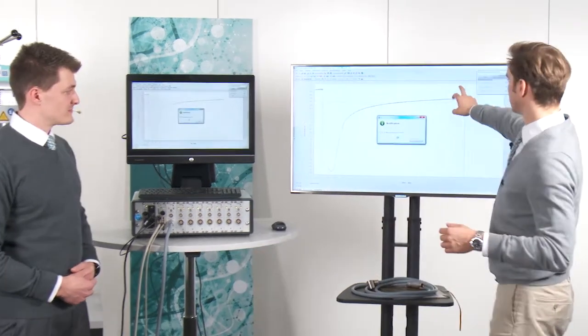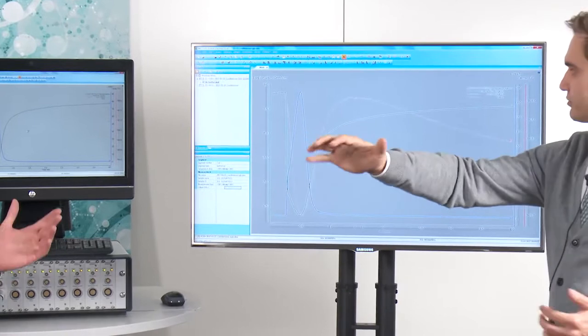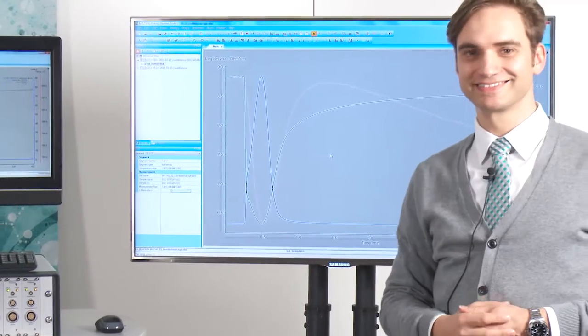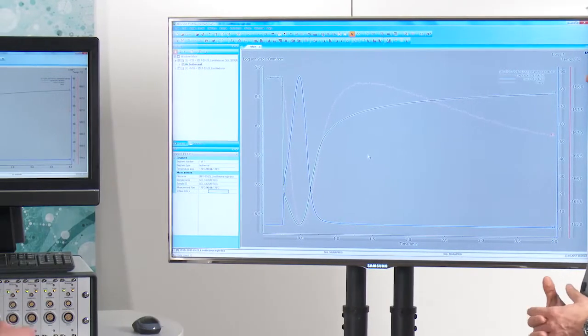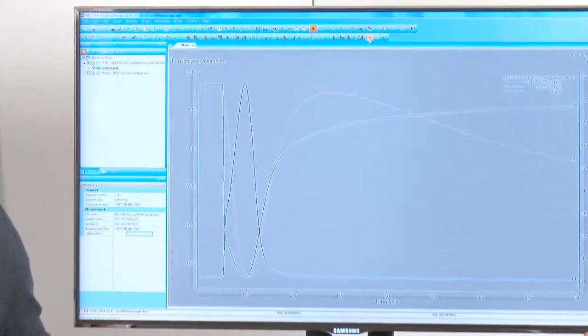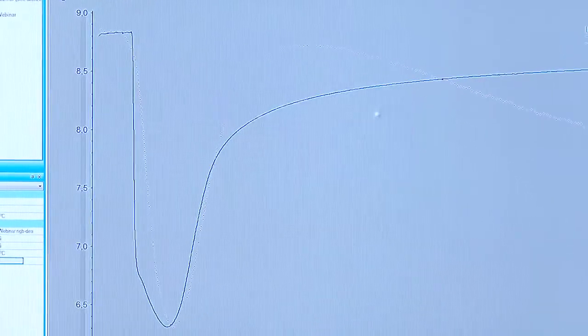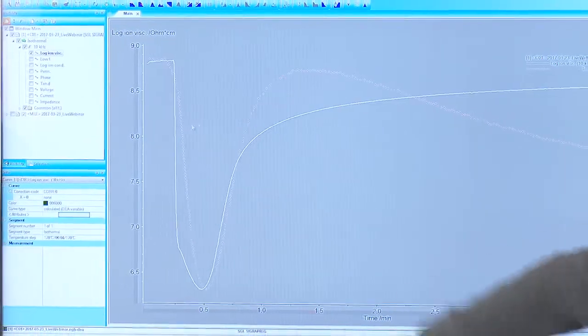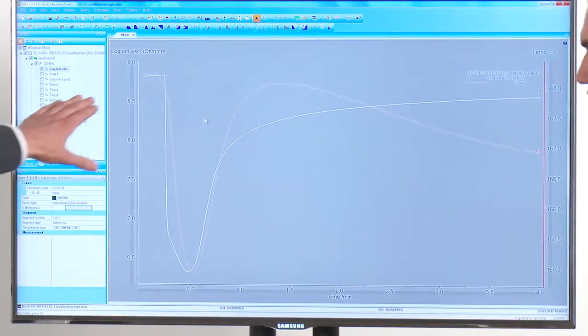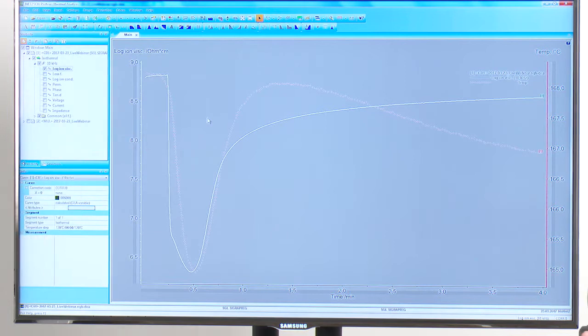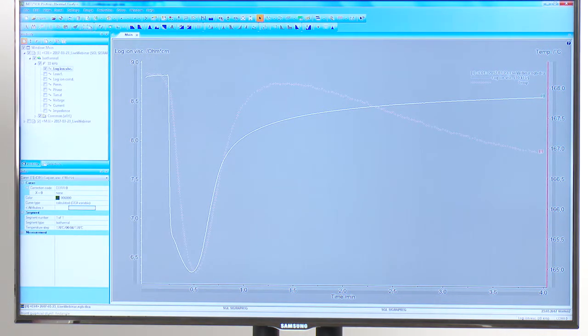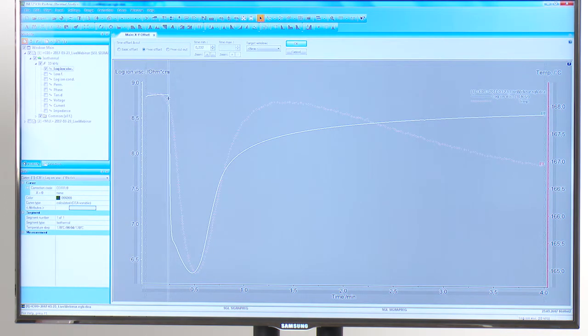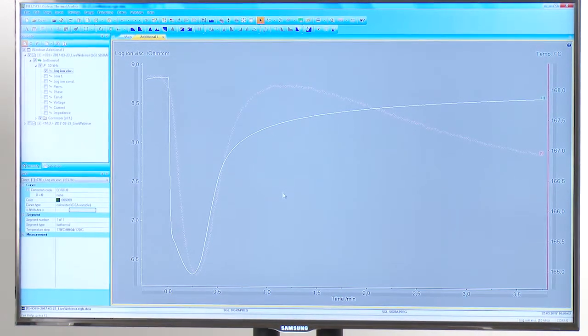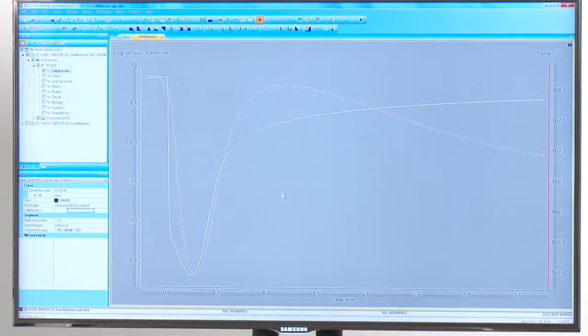So let's go back. You saw the measurement just finished. What will happen next? Yeah, you could see that the software automatically shifts to the Proteus analysis part. So here we can see the just recorded measurement. We only will have a look at the ion viscosity, so the green curve you can see here. As you could see, I started the measurement before I put the sample into the mold. So what we will do now is shift the signal to the point where the measurement really starts, so where the sample got into contact with the sensor. This point of the very sharp increase is now our point in 0 time.